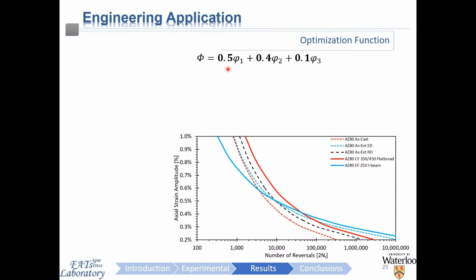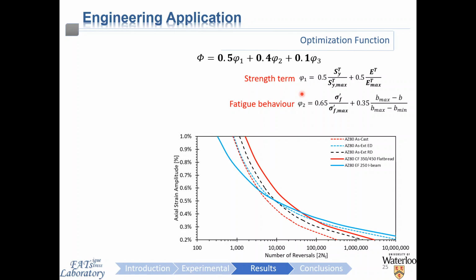performance. The first term, which is phi1 here, describes the necessity of the component to have a high strength and toughness. Non-dimensionalizing these individual property attributes against the maximum observed over the wide range of processing conditions allows us to have a term which reaches a maximum value at unity, or a value of 1. The second term incorporates the fatigue behavior in terms of parameters extracted from an SN curve.